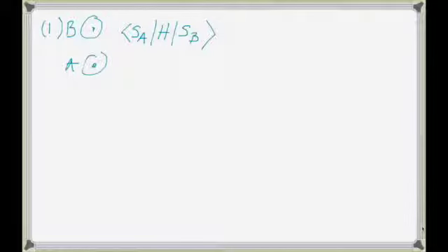And that's defined as V_ss sigma, sort of following what we talked about last time. It's a sigma type bond, and it's between 2 s orbitals. And this is just a notation that goes back to the 50s. And this is going to be less than 0 for the same reasons that we've talked about from day 1. Right? Because the potential is negative, the orbitals are positive, the integral gives you something less than 0, just like our t's.